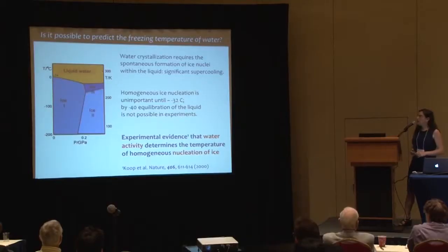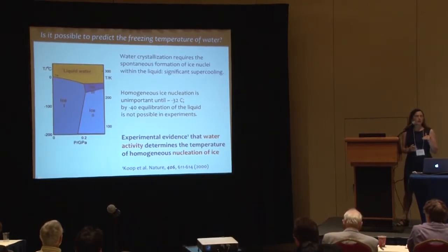The main question I want to address is what determines the freezing temperature of ice. This temperature is critical for many areas, from cryobiology to atmospheric sciences. The main question is what is the rate of crystallization of water and how can we predict the temperature at which water is going to freeze unavoidably on cooling. To produce ice we have to go below the melting point — the equilibrium melting point — because nucleation of ice requires the formation of small nuclei spontaneously, which requires an activation energy.